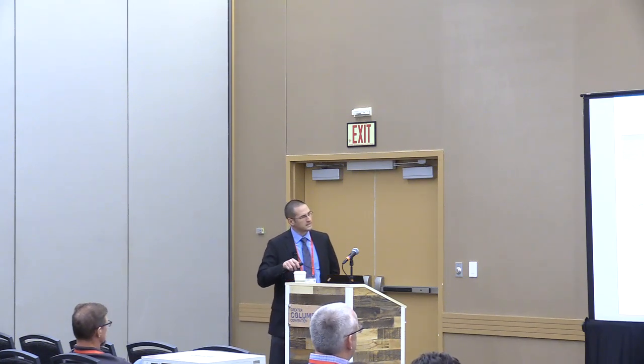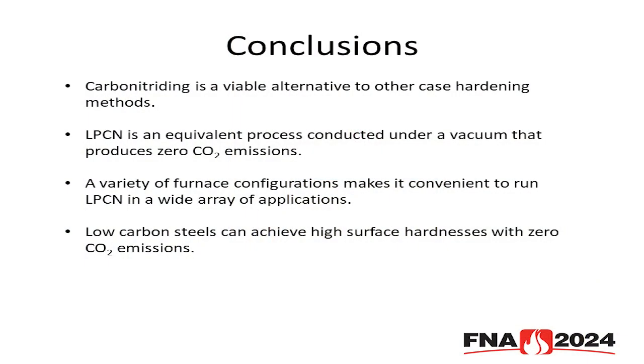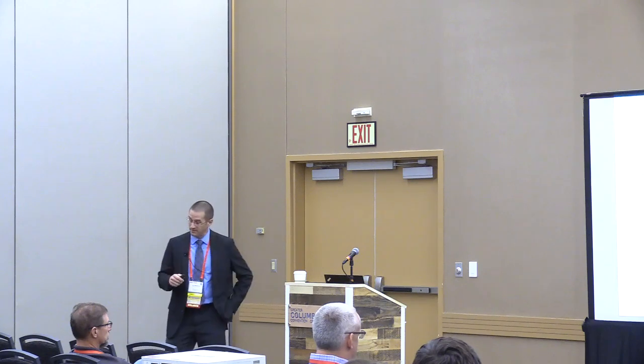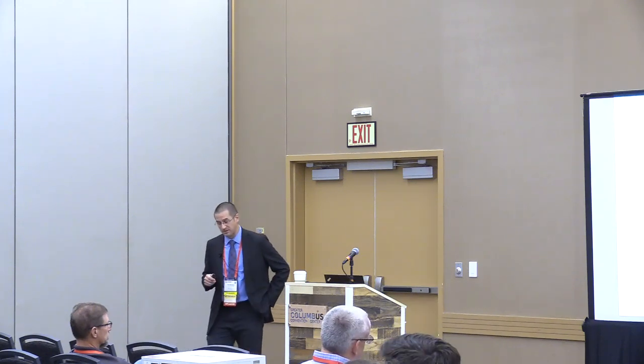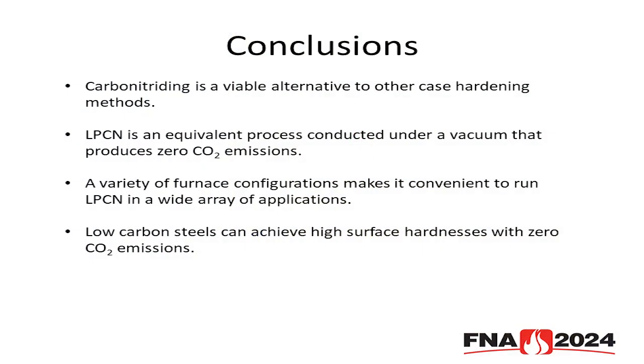So, with that said, a few conclusions. First, carbonitriding can provide a viable alternative to other case hardening methods. Low pressure carbonitriding is an equivalent process that can provide a zero CO2 emissions alternative to carbonitriding. There's a variety of furnace configurations available, so the equipment is not a limitation for this. And low carbon steels can be improved to meet higher hardness requirements without CO2 emissions.